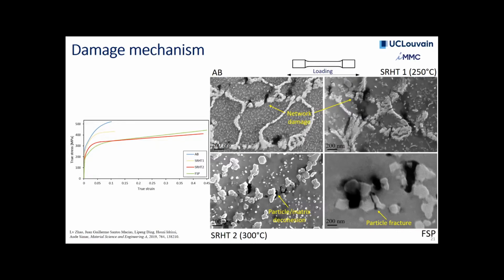But our feeling at this stage of these results is that it does play a role in the coalescence mechanism, the porosities, I mean, because these porosities favor the final coalescence mechanism. But really at the early stages, not so much, and this is really what drives it. So I would say that the porosity doesn't matter so much. Okay, no, I understand.